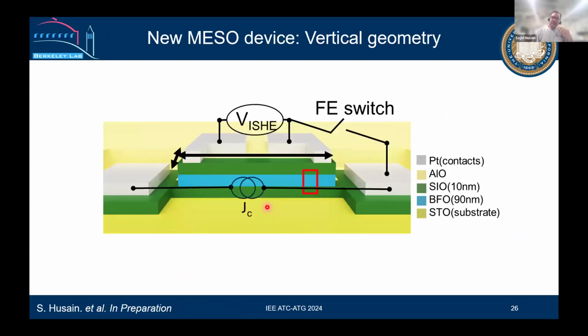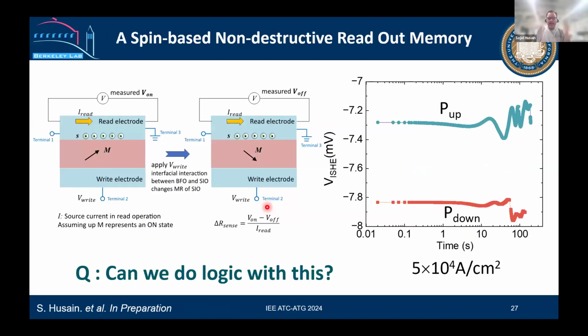And the final idea is, as I mentioned, the idea was to get a vertical device, but it's not so easy. A lot of intense fabrication and growth process is involved in that, but we made it. And now the output voltage is about a millivolt. In the same geometry, we use the current here or current here, and we measure the voltage output. It's the magnetization changing using the electric field. P up means you go from plus electric field to minus electric field, and you can manipulate your stuff using electric field. Now the output is about a millivolt.